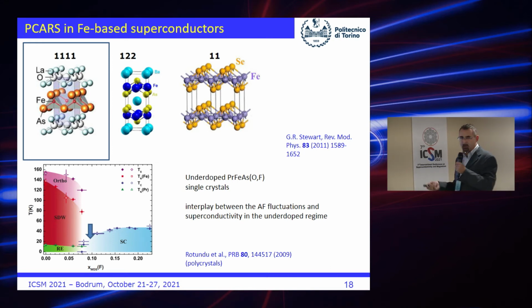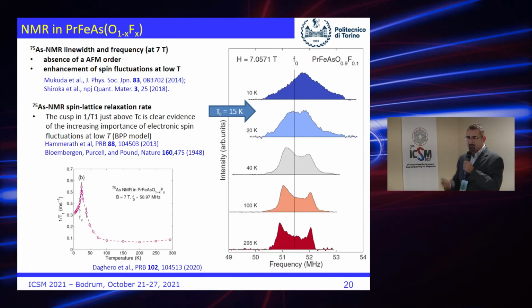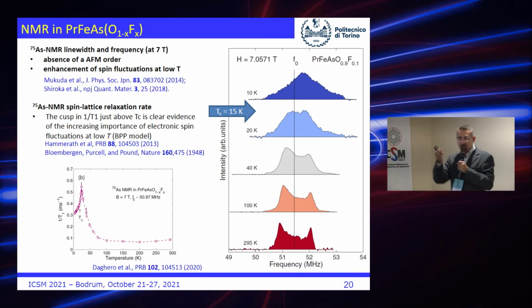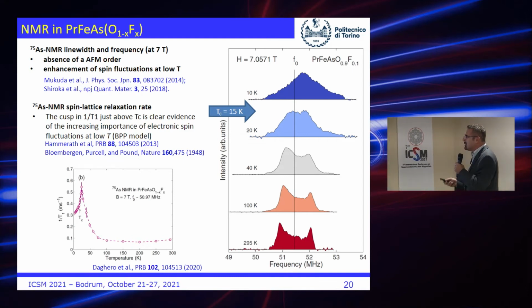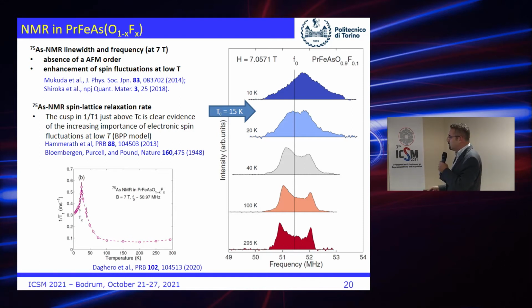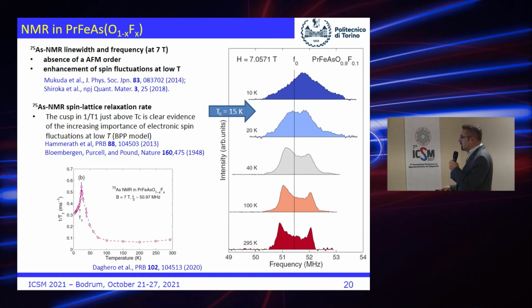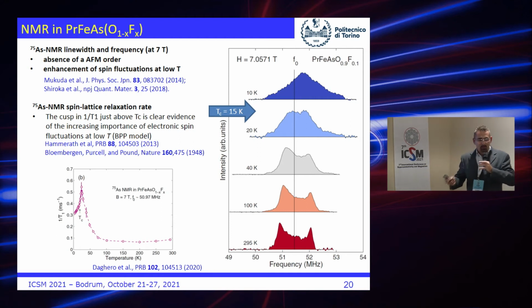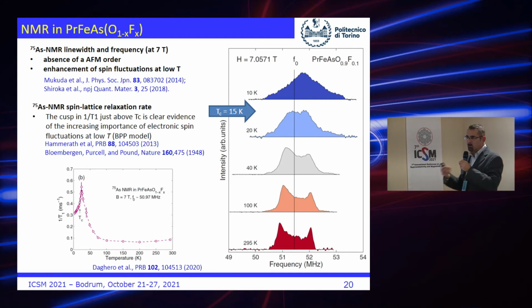And that spin fluctuations are strong and exist is told to us by NMR data. If you have questions about the NMR data, don't ask me, ask Tony, because he made the measurements. So in really few words, what we see is, if you look at the line, you see that there are two maxima that slightly merge into one. And you see that the position does not change, at least in the normal state. Then there is a small shift to a higher energy, and the line is slightly broadened. All these things together point towards the existence and the increasing importance of spin fluctuations, not only of the iron but also of the praseodymium.